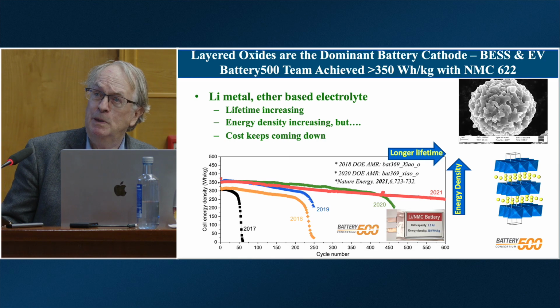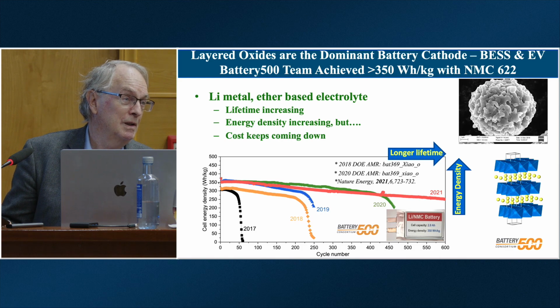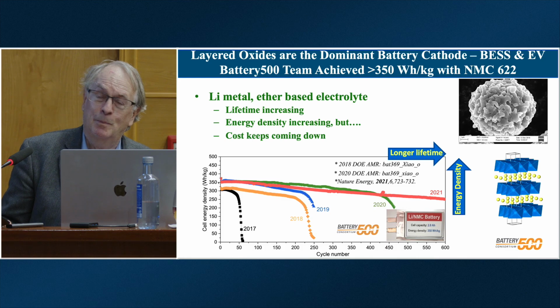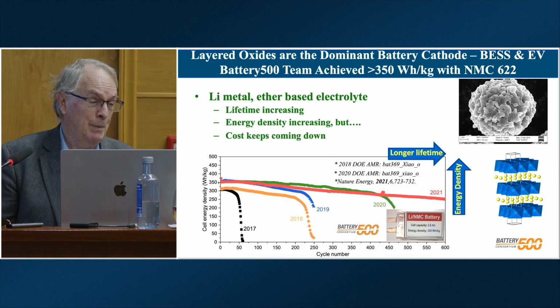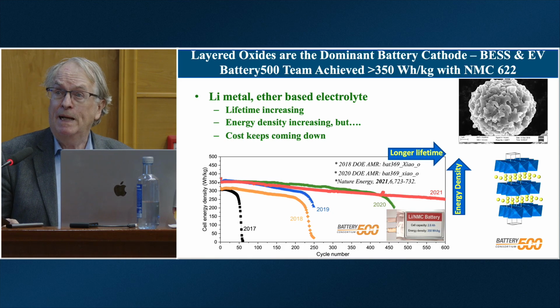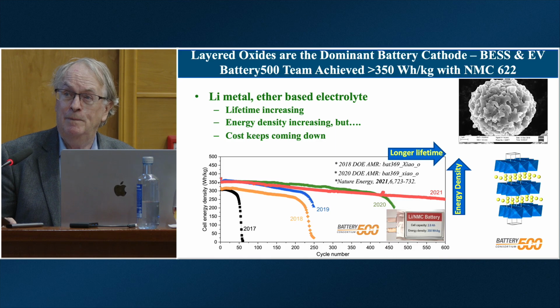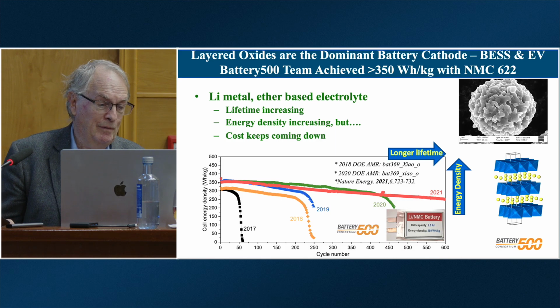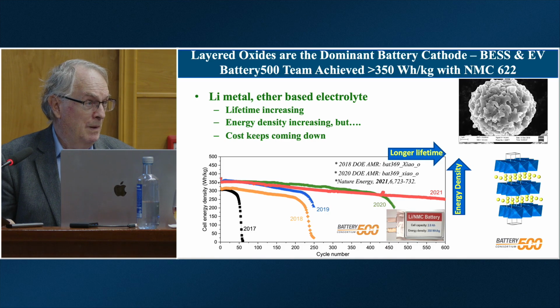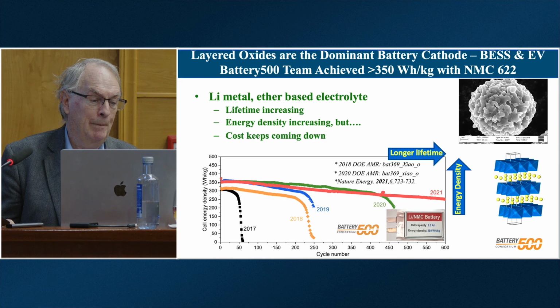So the typical materials we use have this what we call meatball morphology. I've shown you at the top right there. So the primary particles are a couple of 100 nanometers in size. Those secondary particles are about 10 microns, and those pack very well. And the results we've obtained are shown in the bottom there, and these are mostly done by my ex-student, Jie Xiao, who's at Pacific Northwest National Lab.